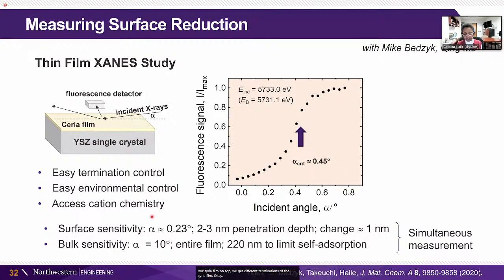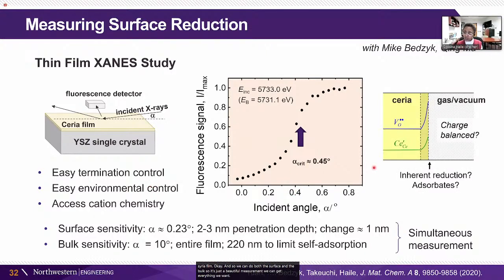Okay, and so we can do both the surface and the bulk. So it's just a beautiful measurement. We can get everything we want. The one thing that we can't detect absolutely is to know whether or not the vacancy concentration tracks with the cerium 3+ concentration. Because what we're getting from this measurement is the cerium 3+ concentration, not directly the vacancy concentration.